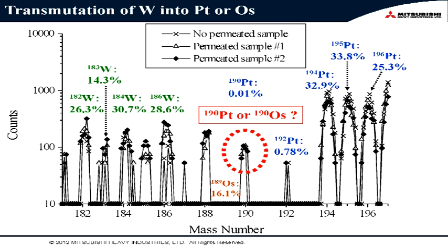These are the results of transmutation of tungsten into platinum or osmium, by SIMS, secondary ion mass spectrometry. In this figure, this is the mass number and the SIMS counts, and the cross means a non-permeated sample, and the triangle and rectangle are permeated samples 1 and 2. And we can see that the mass number 190 increases after permeation, because we cannot see any mass number 190 here. And of course we have tungsten, and also we have impurity platinum.